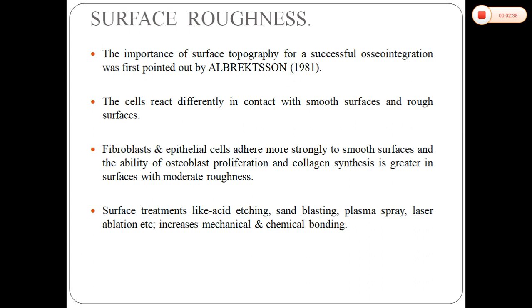Cells react differently in contact with smooth surfaces versus rough surfaces. Fibroblasts and epithelial cells adhere more strongly to smooth surfaces, and the ability of osteoblast proliferation and collagen synthesis is greater on surfaces with moderate roughness. Surface treatments like acid etching, sandblasting, plasma spray, and laser ablation increase mechanical and chemical bonding. These are the additional treatments applied to the implant surface.